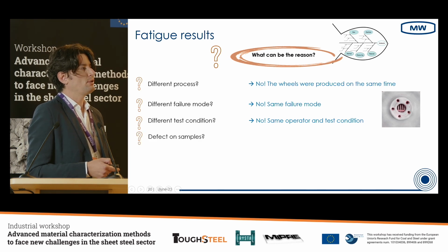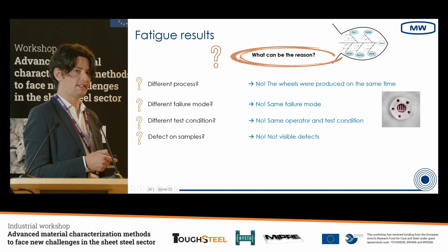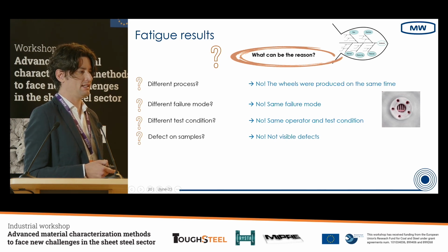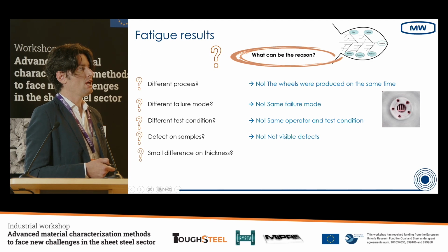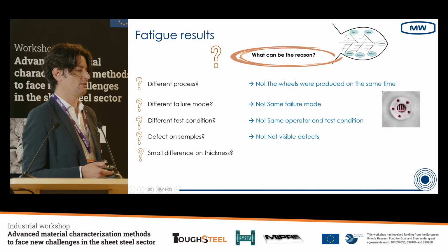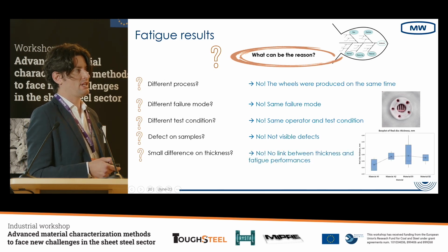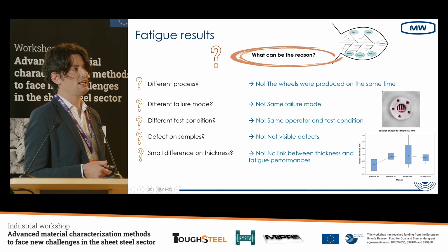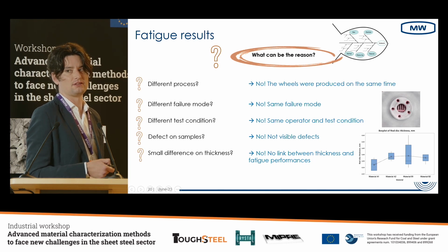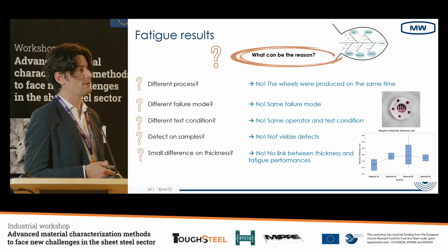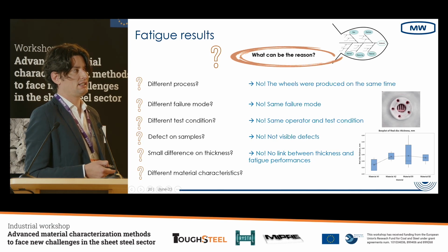Some possible defect on samples? We checked the samples and we didn't see any visible defects. A small difference of thickness? The coil sometimes has some tolerance in the thickness. We analyzed the thickness, and there is a difference, but it does not explain the difference in fatigue, because if you remember, material A was better than material B, but in that case the thickness is not. It doesn't explain this behavior. So different material characteristics. Okay, probably this is the answer.